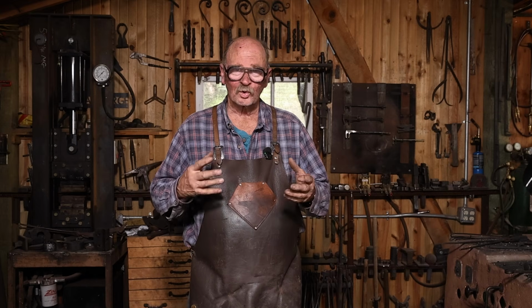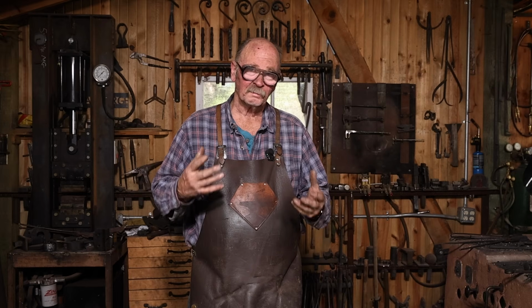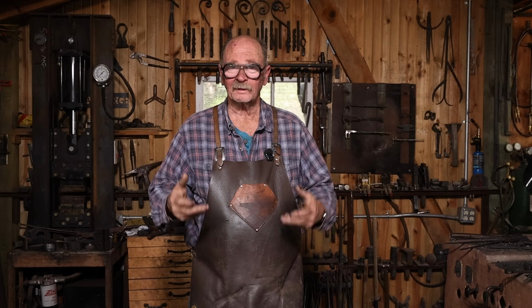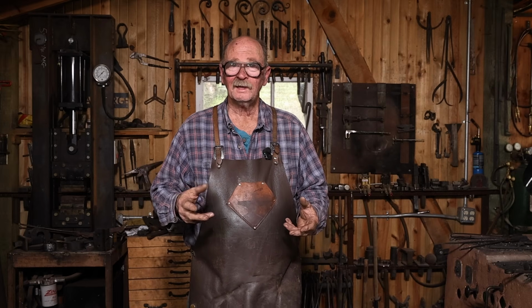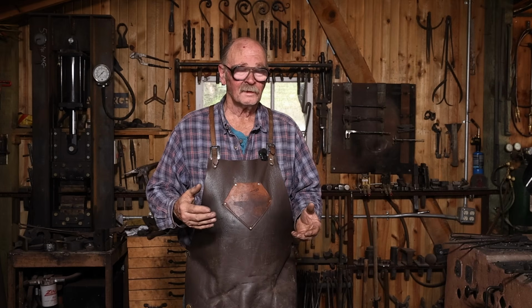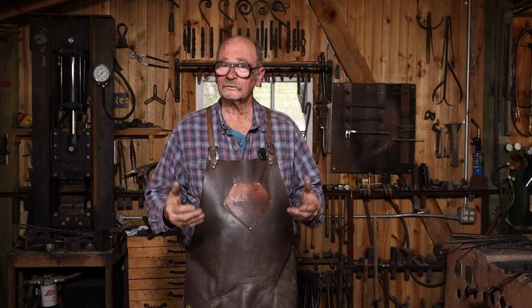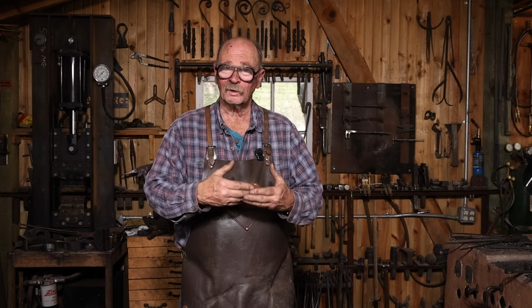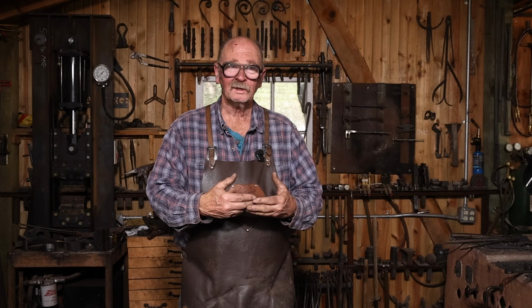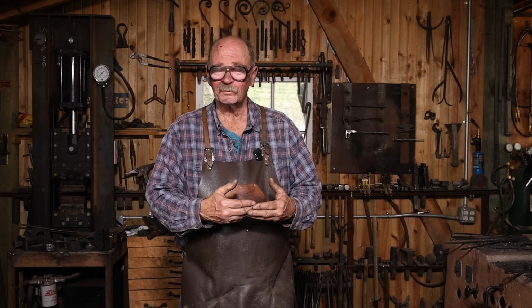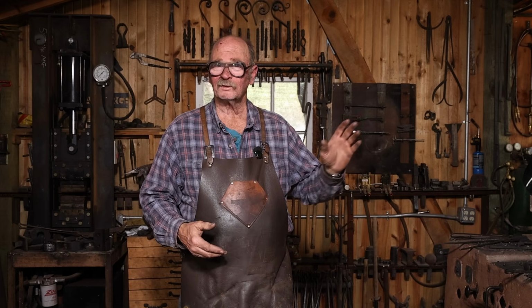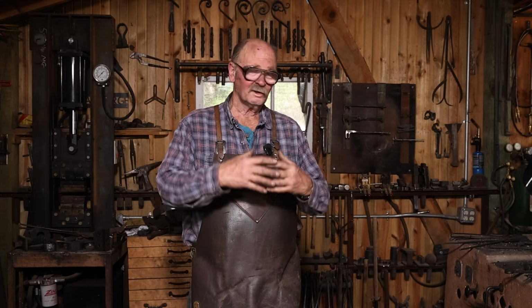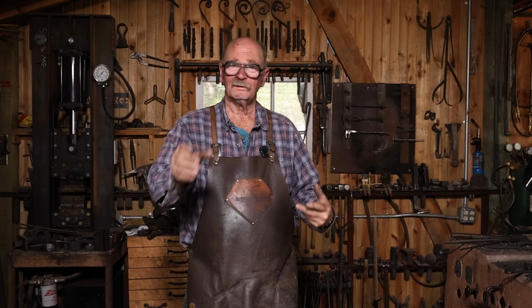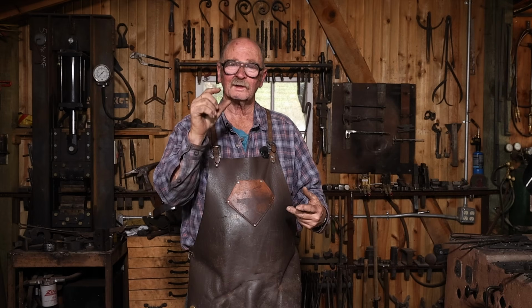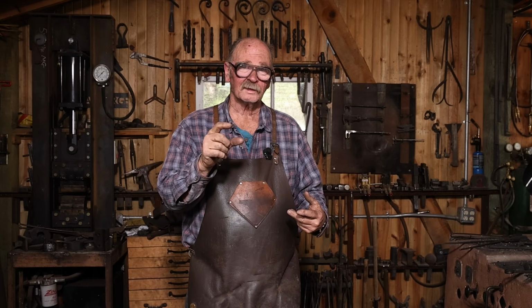Gas forges are great for bigger forge welds. If you're doing pattern welded steel, you're welding up axes, adzes, things like that, a gas forge is wonderful. For welds that are two pieces, like doing a set of tongs and bringing the reins and the jaws together at the anvil, I find gas forges to not be real practical. And even for doing this fire poker weld, you're heating up a huge amount of material for a little tiny weld zone. So I don't really like gas forges for that.